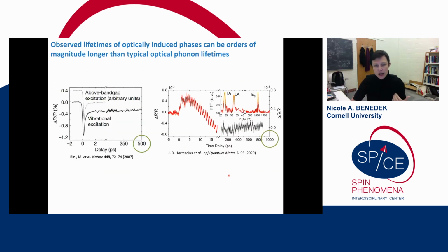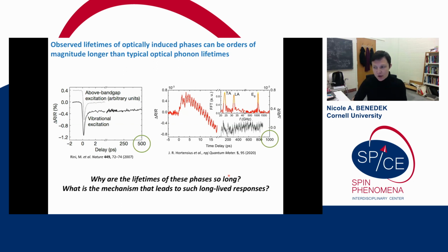But if we look at the observed lifetimes in some of these experiments, 500 picoseconds, 1,000 picoseconds, this is orders of magnitude longer than the typical optical phonon lifetime. So these lifetimes of these metastable phases can't just depend on the IR mode lifetime. It has to be something else. So we think we have a tentative answer to these questions now.